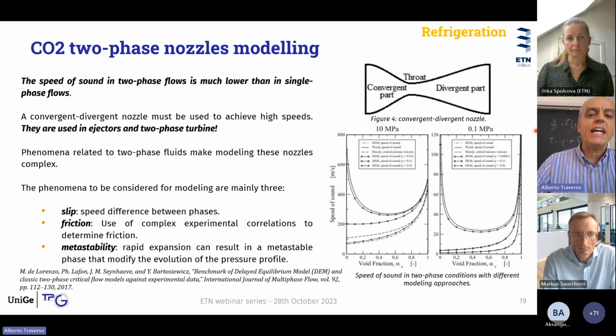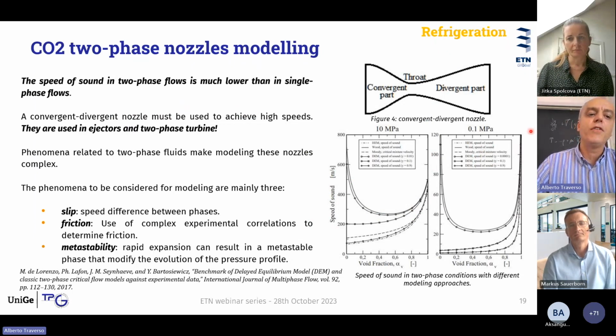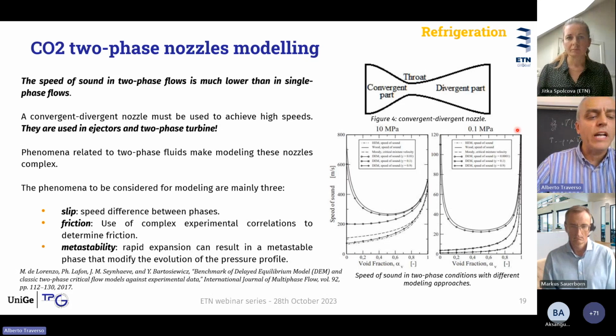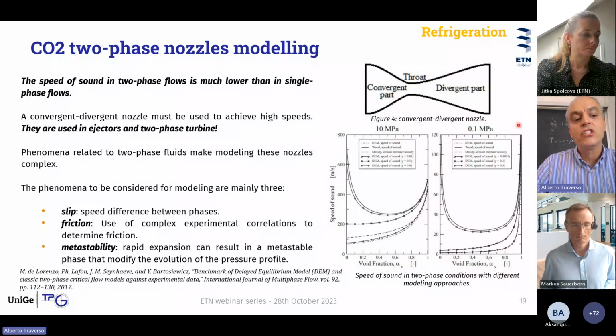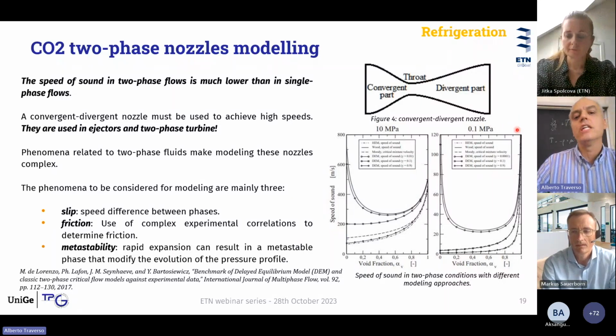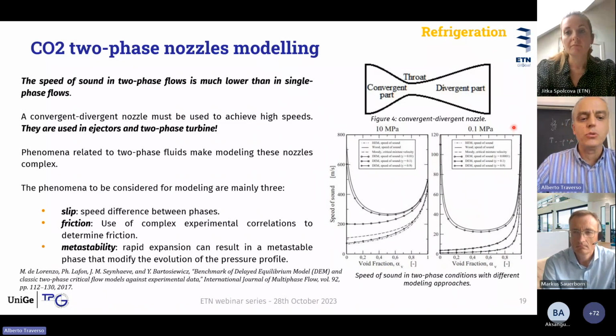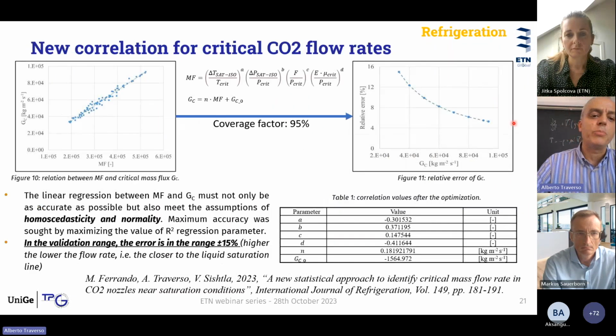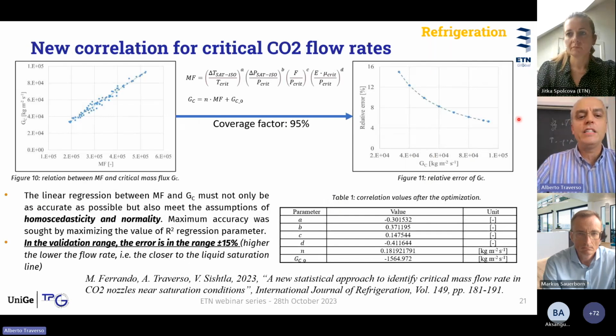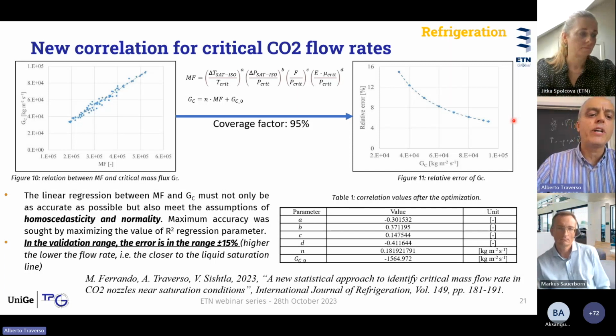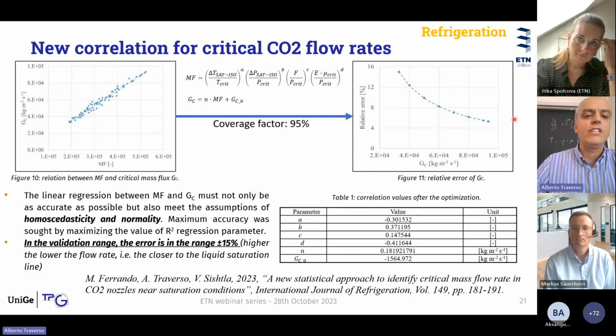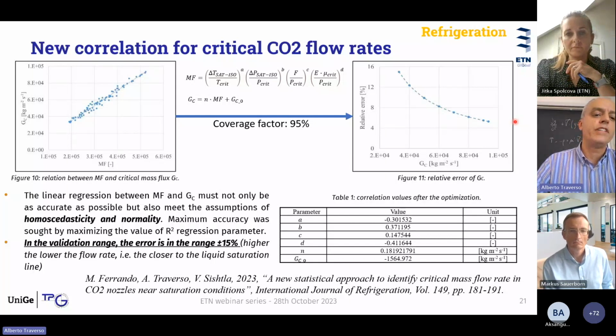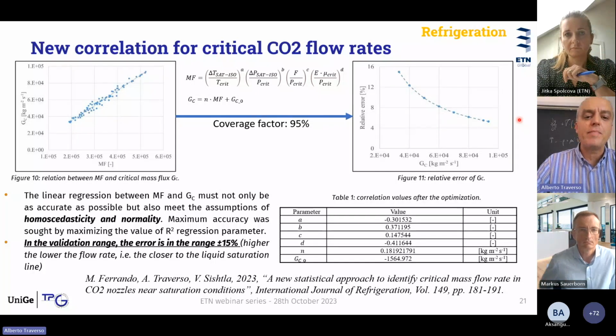And I'd like just to remind here that there are a lot of challenges for modeling and designing two-phase nozzles. In particular, the approach should tackle a number of phenomena which are not present in normal single-phase flow, such as slip between the two phases and friction. The friction loss becomes more complex due to the two phases. And then finally, also metastability, which is well known in steam expansion, especially in the nuclear steam turbine field. Recently, we developed a work also based on original data provided by a refrigeration cycle manufacturer, and we were able to produce an empirical correlation able to predict the critical flow across two-phase nozzles with an accuracy of 5% average relative error.